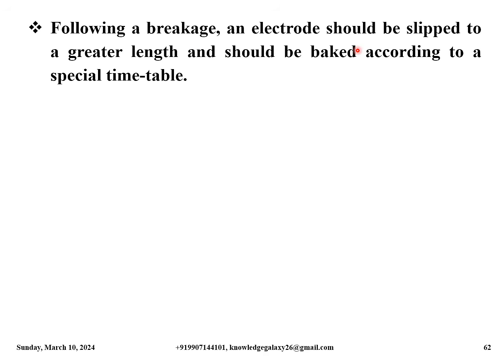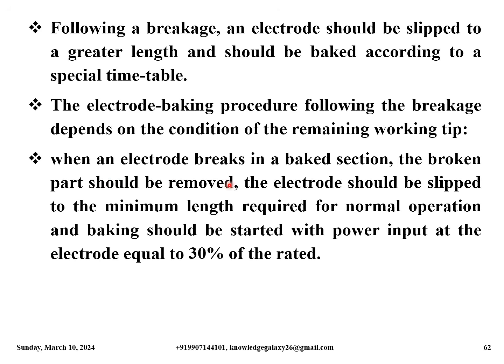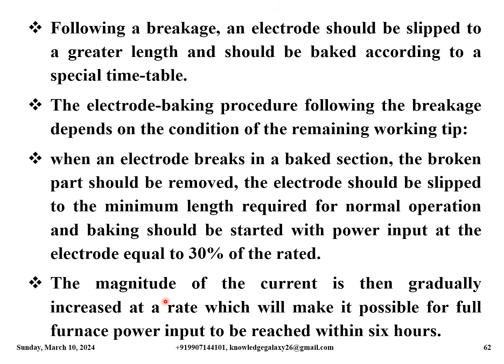Following a breakage, an electrode should be slipped to a greater length and should be baked according to a special timetable. The electrode baking procedure following the breakage depends on the condition of the remaining working tip. When an electrode breaks in a baked section, the broken part should be removed. The electrode should be slipped to the minimum length required for normal operation, and baking should be started with power input at the electrode equal to 30% of the rated. The magnitude of the current is then gradually increased at a rate which will make it possible for full furnace power input to be reached within 6 hours.